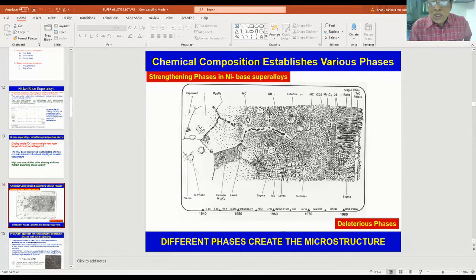Then you see that when all these refractory elements combine, they form some phases known as TCP phases, topologically close-packed phases. All of them are detrimental. They are known as deleterious phases because they impede the ductility of the material. These phases are known as Laves phase, sigma phase, mu, and so many other things. They generally form in the form of needles and platelets, and processing is also difficult if these shapes are present. At the same time, when these phases form, the matrix is robbed of the alloying elements, and the strength and ductility of the material will go down.